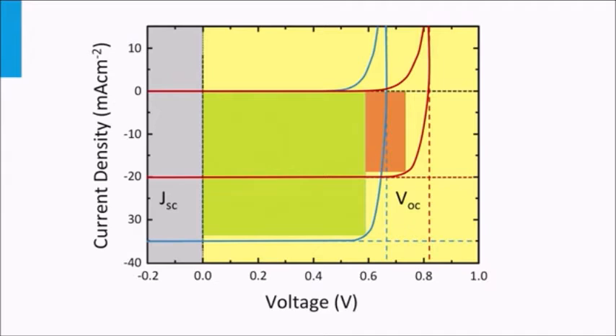The JV curve of the solar cell with the low bandgap material has a larger short-circuit current density, whereas the open circuit voltage is smaller. An important conclusion of this simple exercise is that the choice of semiconductor material determines the open circuit voltage and the short-circuit current density through its bandgap.